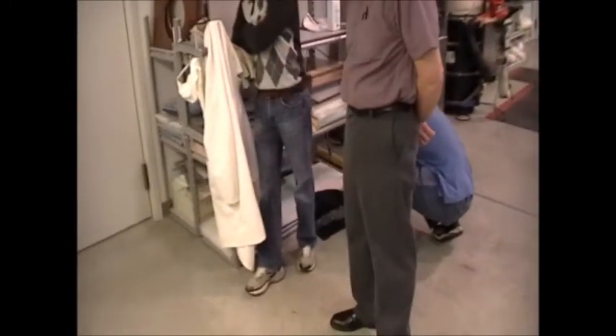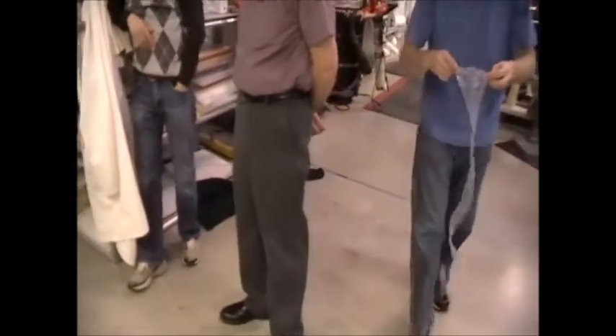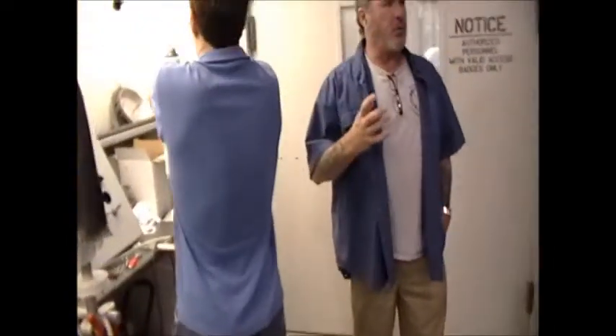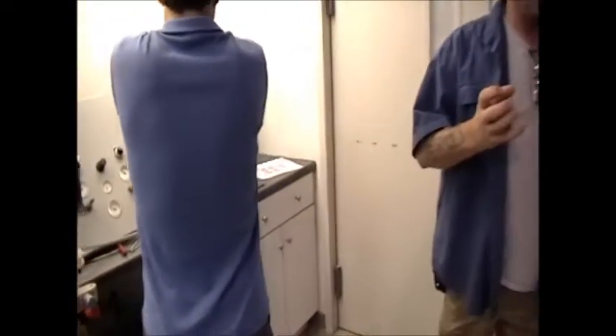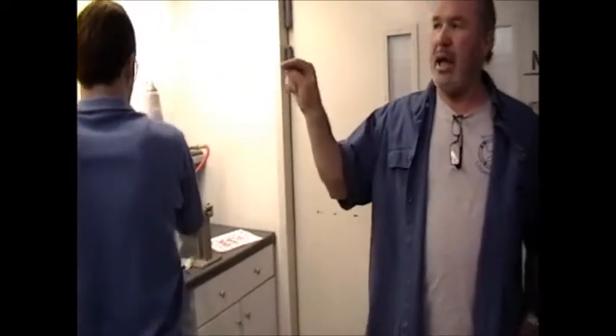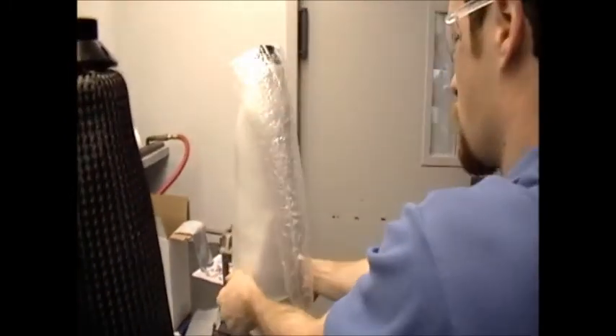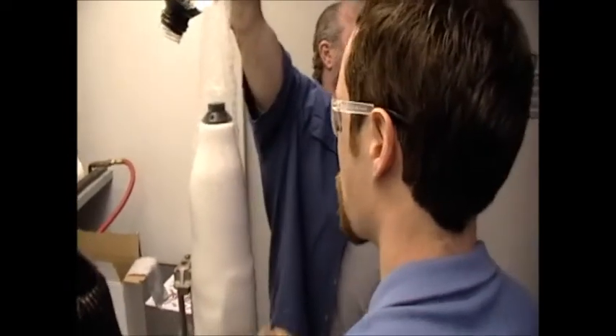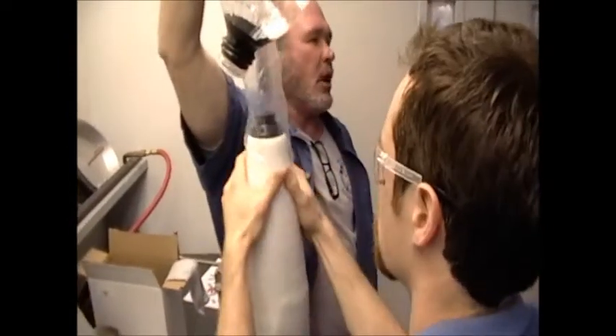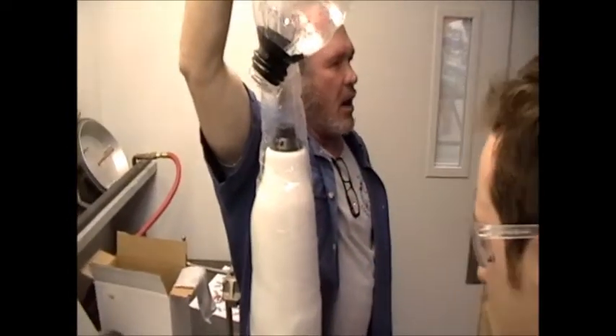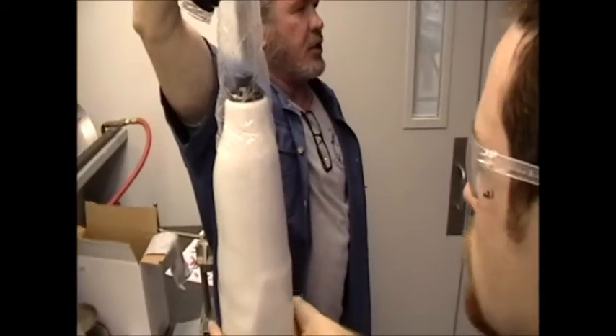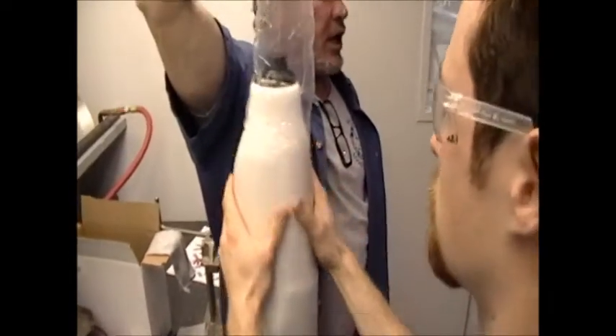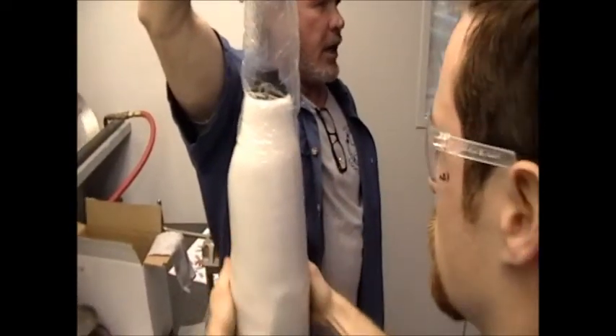And my socket will not come up, especially the first day that we, yeah, no holes. The first day that we laminate today, the epoxy resin will not be as hard, as rigid in my socket as the graphite will. Okay. But by tomorrow morning, it will be so. Yeah. The epoxy takes a total of up to 24 hours to finish curing. Okay. But the key is, is that within two hours of laminating, we've got it off of the model and we're working with it. We're polishing the edges and with no fear that it's going to alter or change shape. Right. Okay. It's set up enough for that.